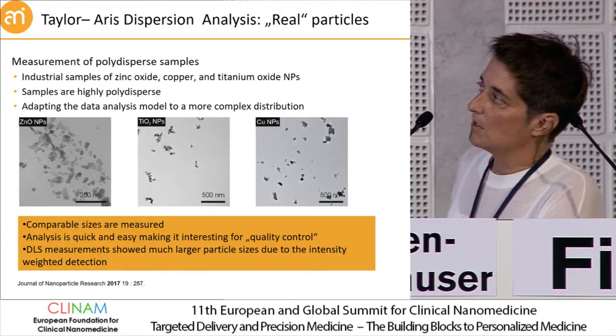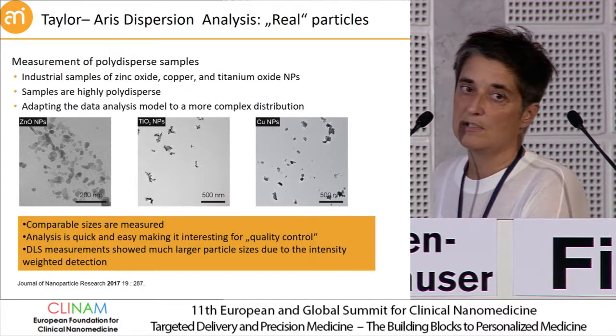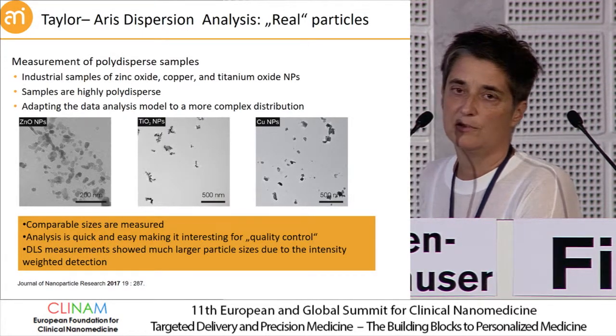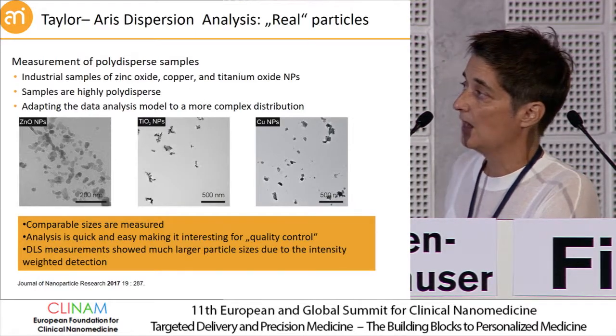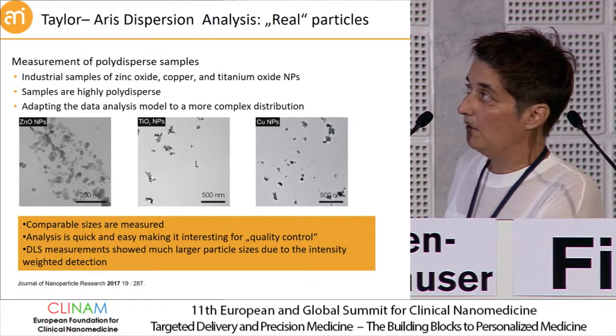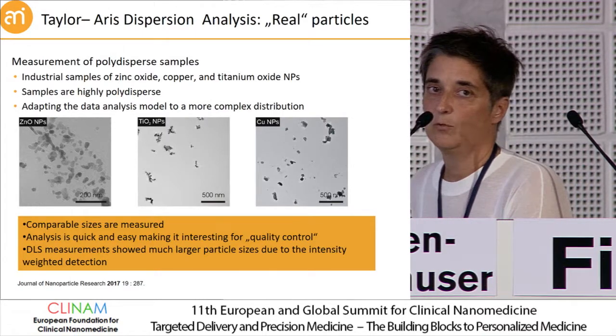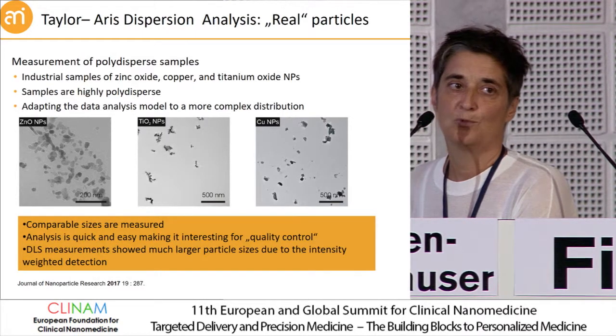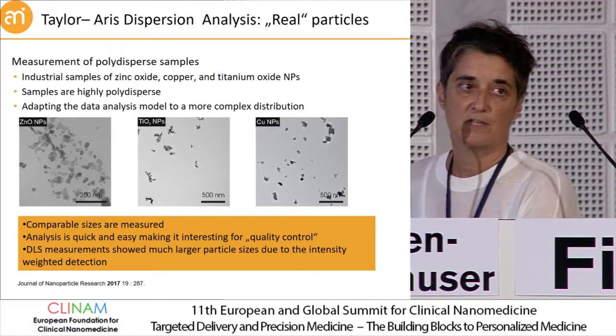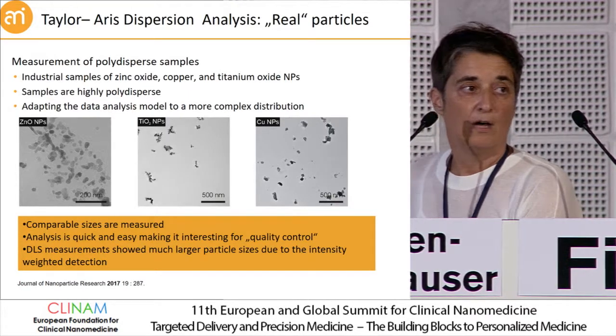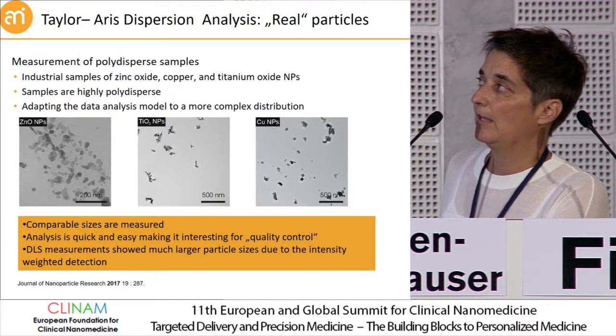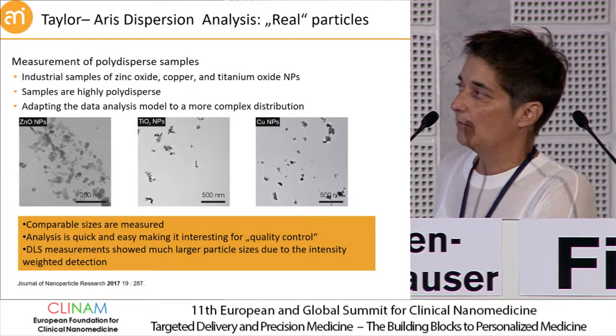We looked at zinc oxide, titania, or copper particles, something that is very difficult to reliably measure in DLS. This actually worked very well, but I cannot hide that we have to adapt the algorithm which we're using to fit the functions. Also, this is no black box, where you just input a particle and click a button. So you will have to look at the data really carefully.